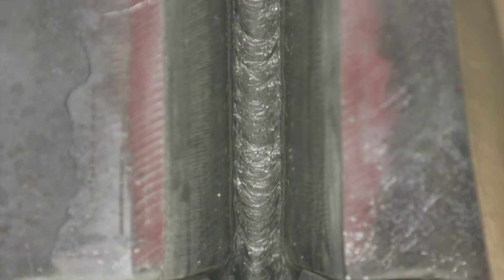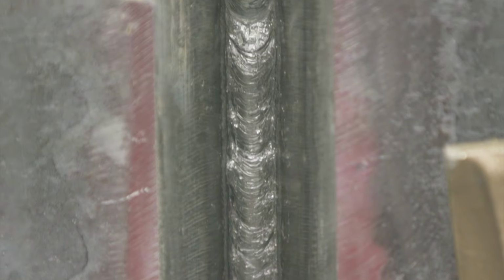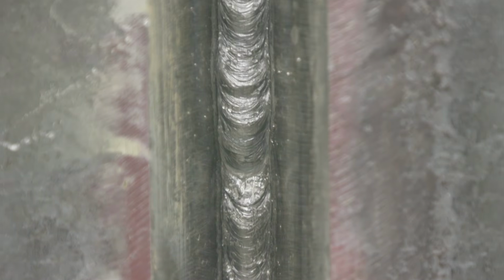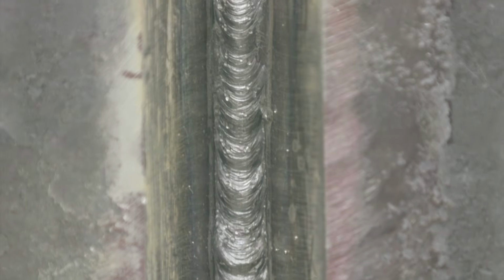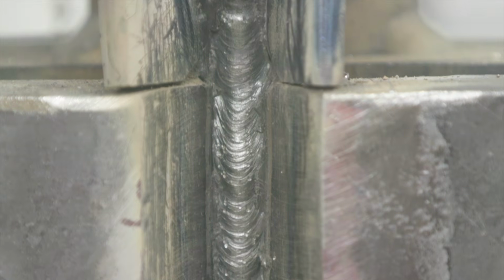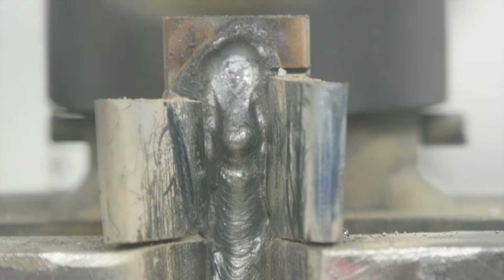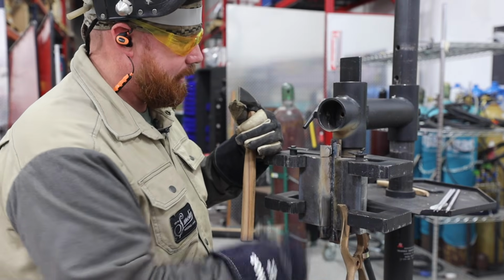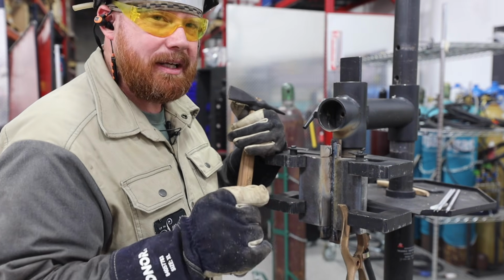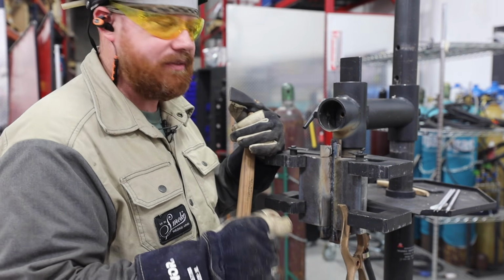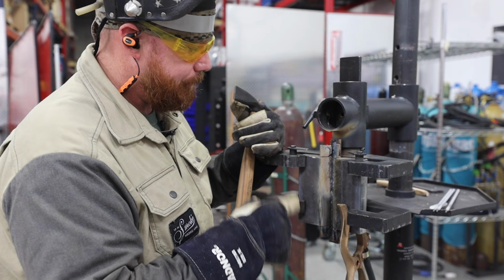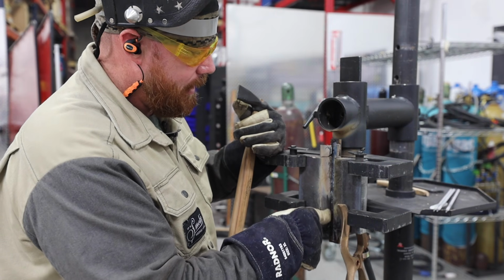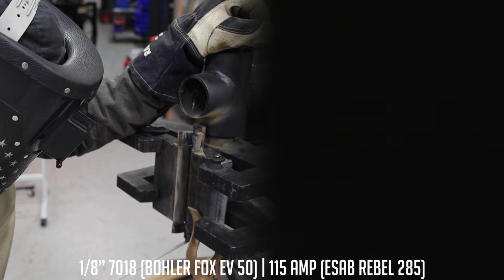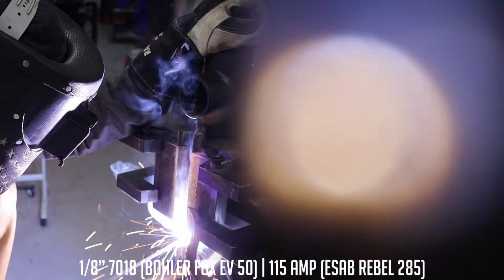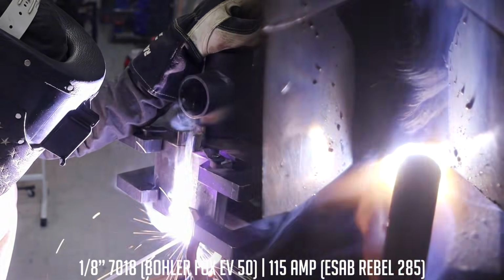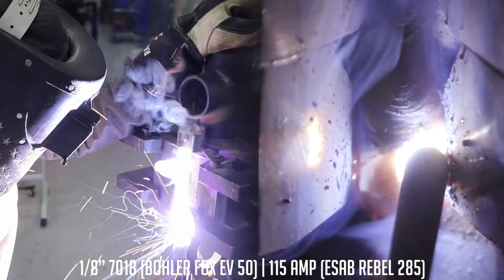Once I jump out of those ranges, if I went less than 100 with this specific rod or above 140 amps, now I need to actually write a procedure for it. But because I'm staying within the manufacturer's specs, we should be good here. I'm going to go ahead and clean this out and then run that next pass. It's just going to be a little bit wider stringer. I'm not running weaves on this, but it's going to be a wider stringer. My goal is just to cover up that root pass. You shouldn't see any of it. After that point, I'm going to go ahead and put my weld layers in there with stringers the rest of the way, all the way until we get to the cap.